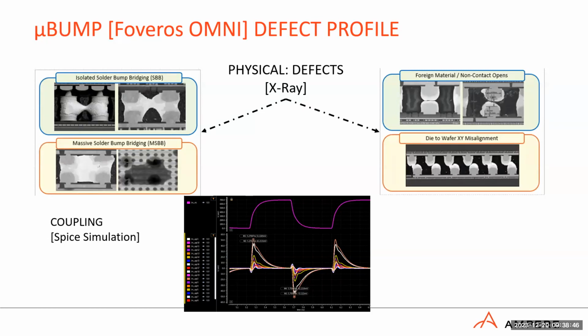Now, these are examples of the kind of failures that we have observed in the case of, say, Ponte Vecchio. This is a 35 micron design. What you see here are that the solder bumps from adjoining interconnects are smeared over. Because they are very, very dense, as a result these two interconnects have got shorted. There are various examples of this, and as it becomes denser and denser, this phenomenon is going to go on increasing. And there are a couple of examples here where not only two adjacent interconnects, but a number of them could get shorted in the same way.